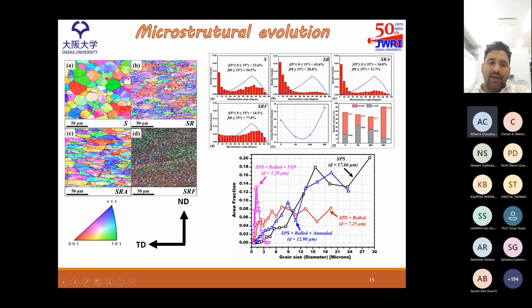And on annealing, the typical recovered structure can be seen, where the low angle grain boundary fraction is reduced, and however the grain size is almost the same or increased, around 13 micron, because of the exposure to high heat. On FSP, a fine equiaxed grain structure is formed, and this structure is completely different from all these three because of its very fine structure.